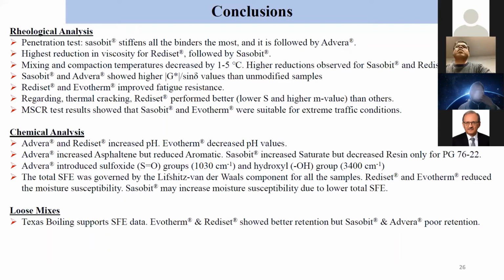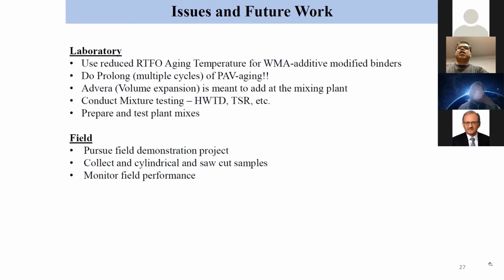And then chemical analysis, we did not go into details, but what we found is that Sasobit may increase the moisture susceptibility due to lower surface free energy. And Texas boiling tests support that Evotherm and Rediset showed better retention of asphalt binder, but Sasobit and Advera had poor retention. Next slide, some of the things I would like to mention.